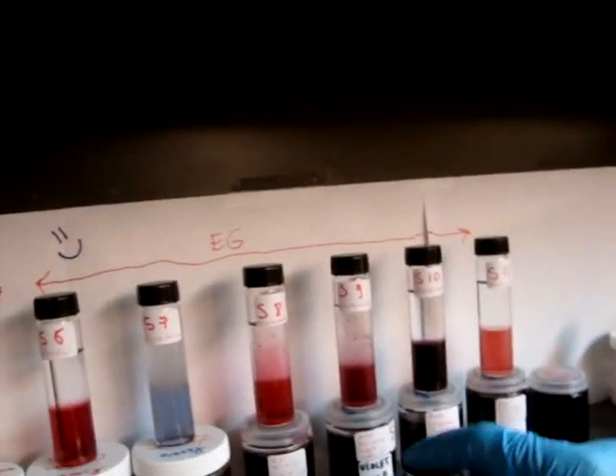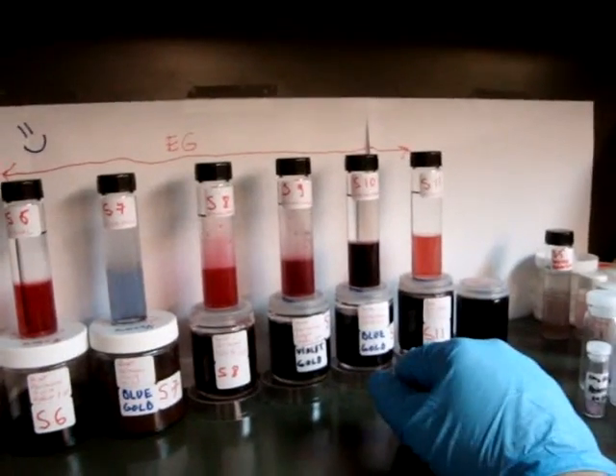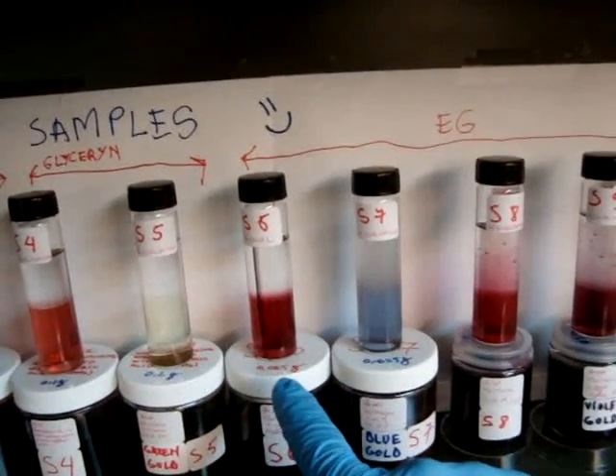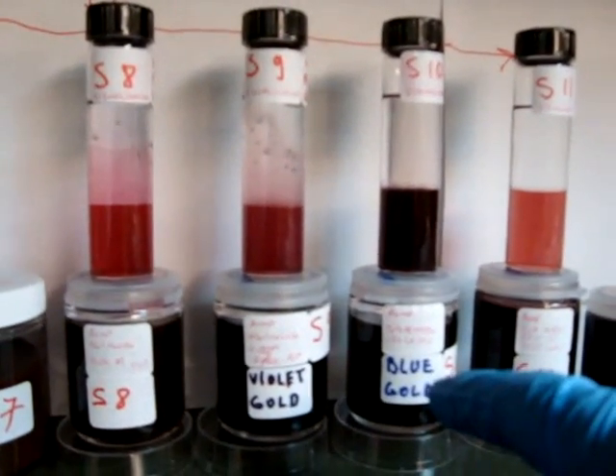What I read from a paper is that as you increase NaOH concentration, the nanoparticle size should actually decrease — which is quite the opposite of what I found. The sample done with ethylene glycol at 0.1 molar NaOH, sample number 6, was actually the smallest size. When I tried higher NaOH concentrations thinking it would reduce nanoparticle size, what I actually created was this kind of violet color, and this is a big size. So they're either wrong in the papers, or there's something off, because it's not in accordance with the results from the papers I've read.